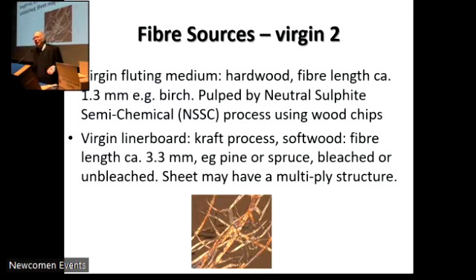And that's made by a wholly chemical process in which we strip out and depolymerize the lignin using a hideous mixture of caustic alkali and sulfur. And that dissolves the lignin as what's known as black liquor. And interestingly, the black liquor can be burnt in the pulp mill like fuel oil. So pulp mills making Kraft products are actually self-sufficient in energy because they can use the lignin to power themselves. And that gives us a brown fiber, which can also be bleached. So you can have a white liner as well as a brown one.